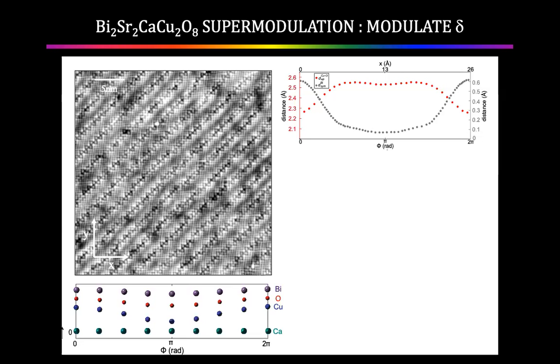Every 9 units, so now this is the CuO2 axis, and this is the CuO2 axis. At 45 degrees, every 9 unit cells, the top surface of the crystal, this is the bismuth oxide layer, modulates from a high elevation down to a low elevation here, and back to a high elevation. So high, low, high, low, high, low, et cetera. Every 26 point something angstroms in this material, the apical distance is changing. That's a fact. So now you have to figure out by how much could it be changed.